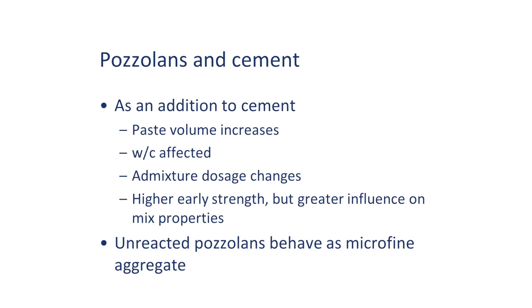You can also add them. Typically this is done if you have, let's say, a concrete truck that's delivered and you want to add pozzolans to it. Well, you can't take cement out because it's already mixed in. You're just adding bags of pozzolans to that mix. Here you're boosting your cement paste volume, and because the pozzolans are counted as part of the cement in the calculations, your water cement is affected. And of course all your admixture doses change and all that.